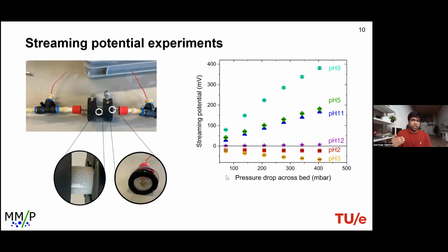Some interesting notions I want to point out from this graph are the values of pH 2 and pH 12. You can see that as you go towards the extreme pHs, pH 2 and pH 12, the slope of the line closes down. This is because of shorter Debye lengths.